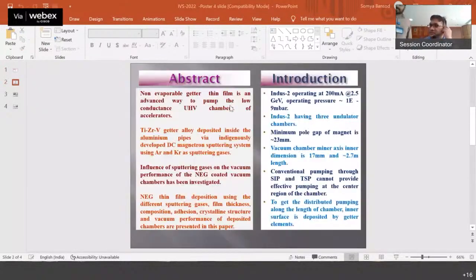Okay, sir. So, sir, NEG is the element which can be widely used to sputter inside the vacuum chamber, and it provides gas molecule pumping on its active surface. So, NEG thin film is deposited to pump the low conductance UHV chamber of the accelerator. Here we have deposited two aluminium chambers using the getter alloy titanium, zirconium, vanadium inside the aluminium pipe via the DC magnetron sputtering system. Here we have investigated the influence of the sputtering gases on the vacuum performance of the NEG coated chamber. So I will describe the NEG thin film deposition using the different sputtering gases, film thickness, composition, adhesion, crystalline structure, and vacuum performance of the NEG coated chamber.